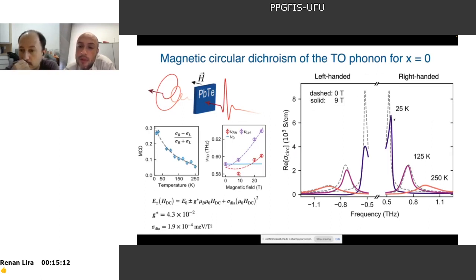This difference means that you have different absorption of circularly polarized light. That means that we have magnetic circular dichroism. The meaning of magnetic circular dichroism is a difference in absorption between light with different handedness, left or right. But this difference is much stronger with magnetic field. At 0 Tesla there is no difference, at 9 Tesla there is a large difference. So what we have is magnetic circular dichroism.